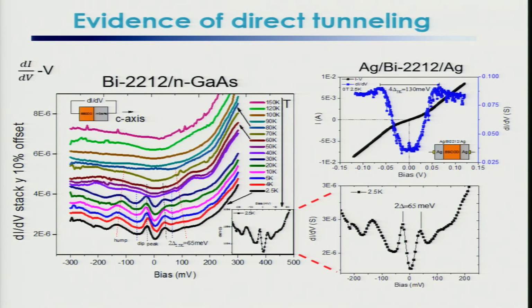We can tunnel in these devices. So again, we showed tunneling because we see the tunneling gap. The tunneling gap agrees with the BSCCO gap here, these features here, and this 2 delta is in good agreement with BSCCO, and we see a single peak here due to the well-known phonon mode in BSCCO, or if you want to call it a phonon mode.